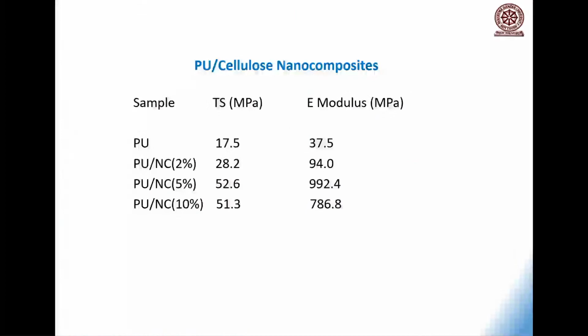Let me show you another interesting slide. This we have done with Brazil. My Brazilian collaborator is very active in making polyurethane, medical grade polyurethane. Look at this medical grade polyurethane. The strength is 17.5, modulus is 37.5. And when he visited my university, he was from Sao Paulo University, we thought of improving the modulus, which is only 37.5.